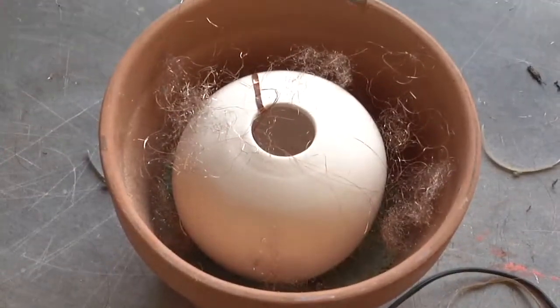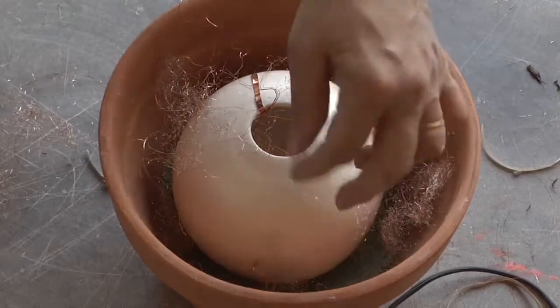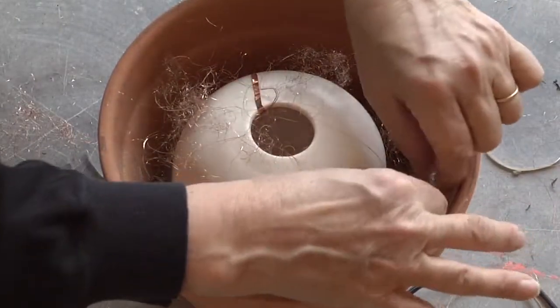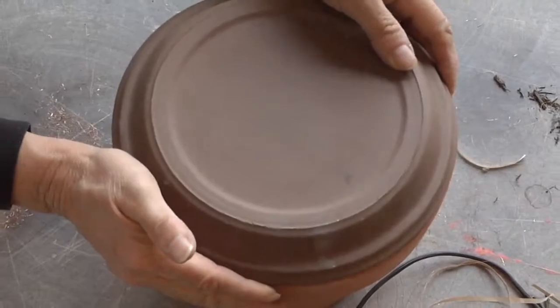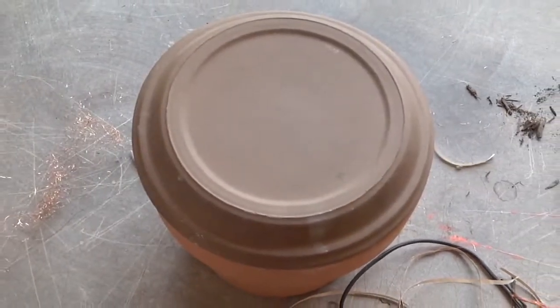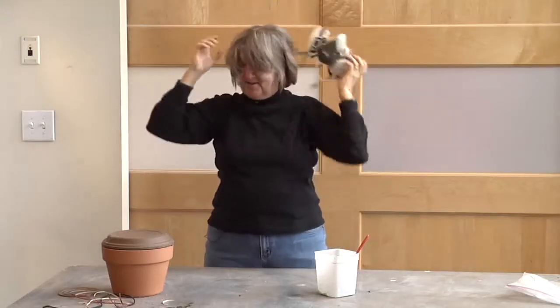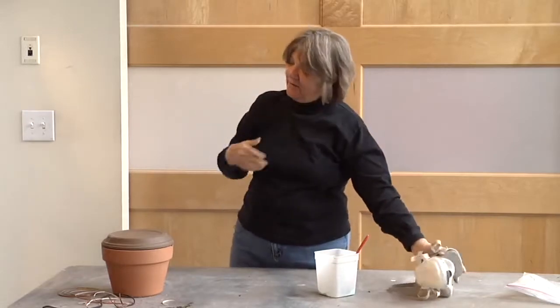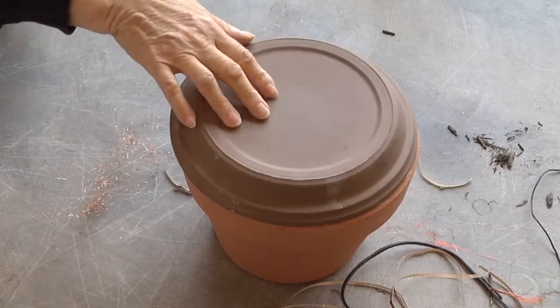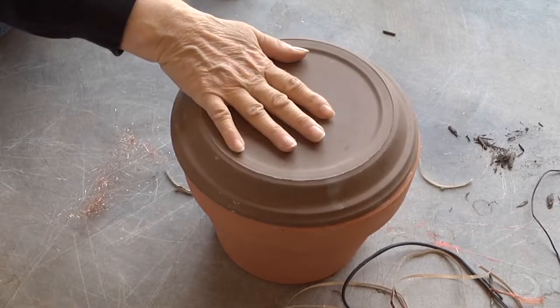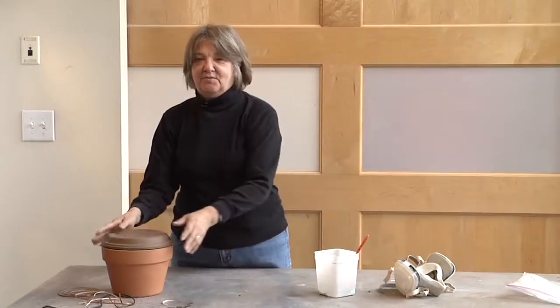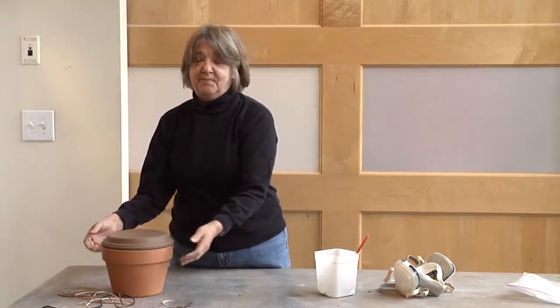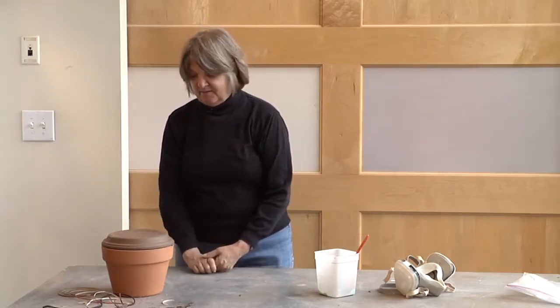Okay, so that should do it, and then I'm going to cover it with a lid to hold the chemicals and the combustion and the smoke and all the activity inside of there. Okay, so now it's ready to go into the kiln, so I'll take it out to the kiln and we will fire it up to about 1650, hold it for 20 minutes, and then let it cool and take it out when it's about 200 or touchable, and see what happened.